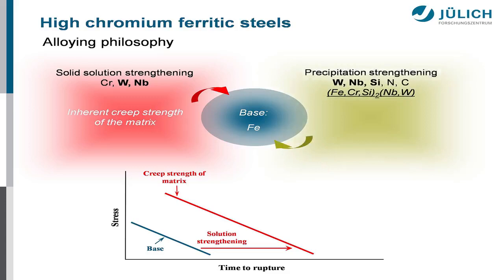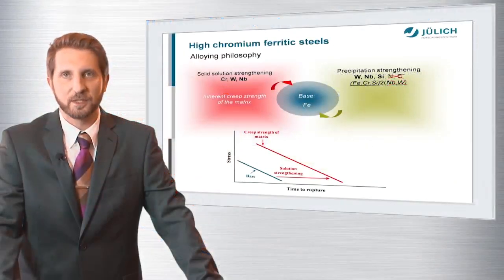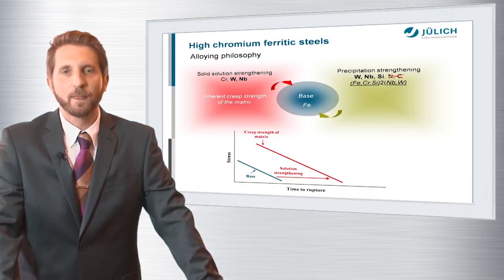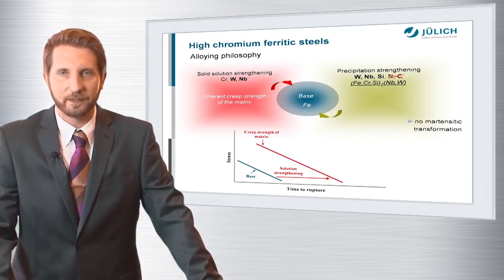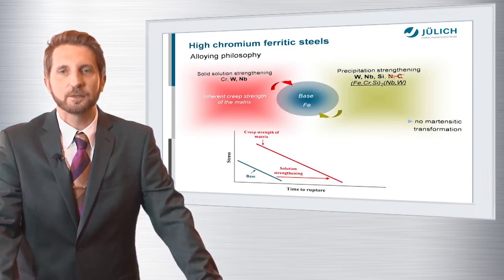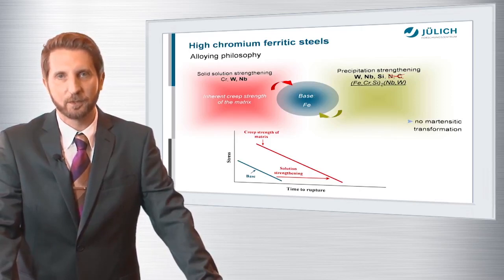You put into some more tungsten, some more niobium, a little bit of silicon. You restrict the nitrogen and carbon contents to very low levels to force the precipitation of a mixed Laves phase. The composition is given up there on the slide. And now I have to point out that our materials are completely ferritic at any temperature, so they do not undergo martensitic transformation upon cooling.